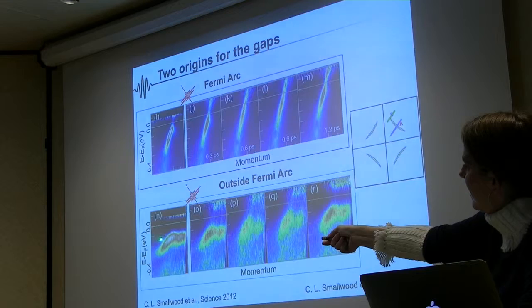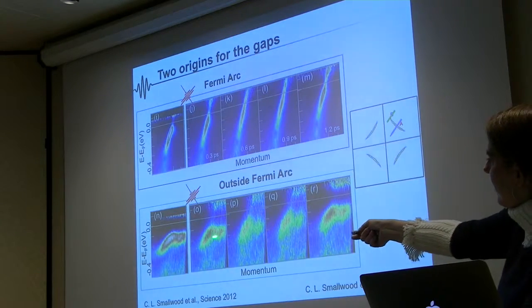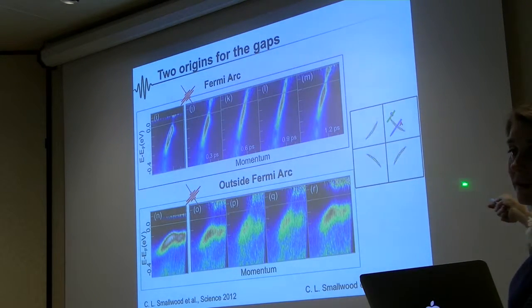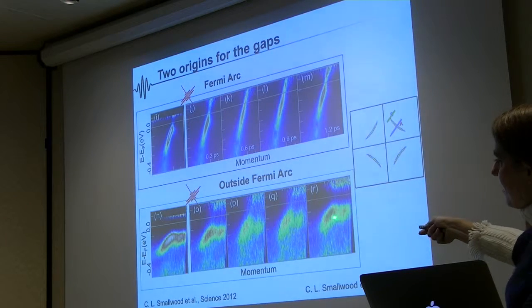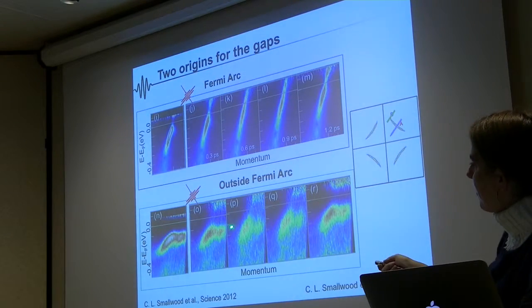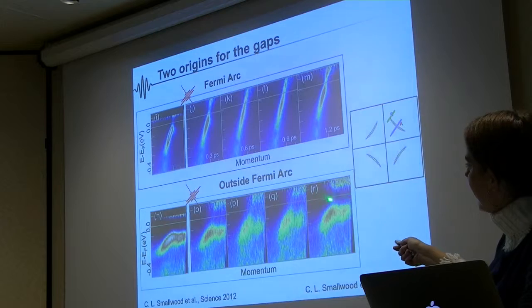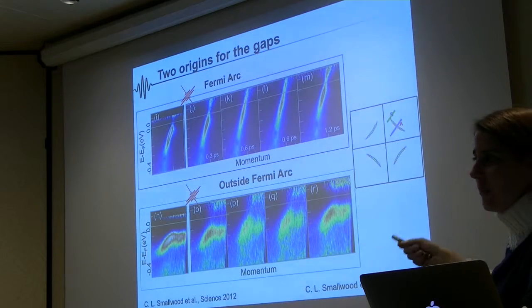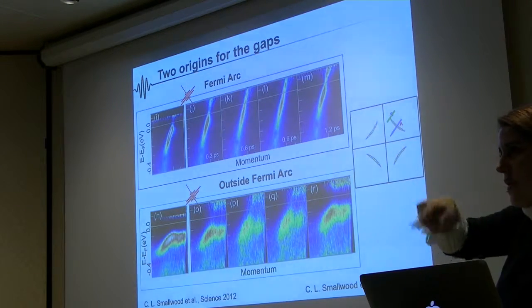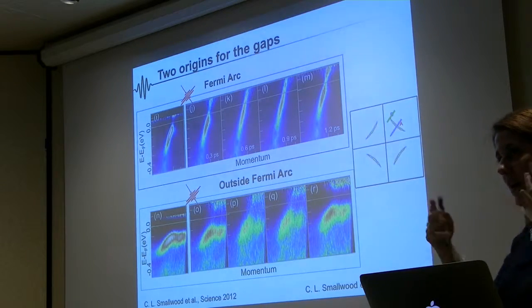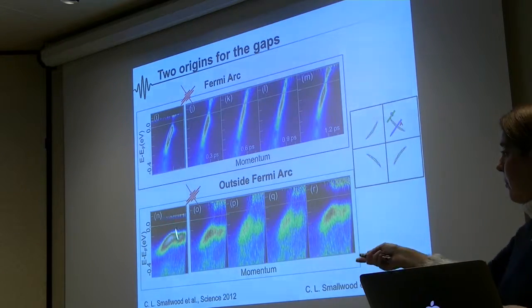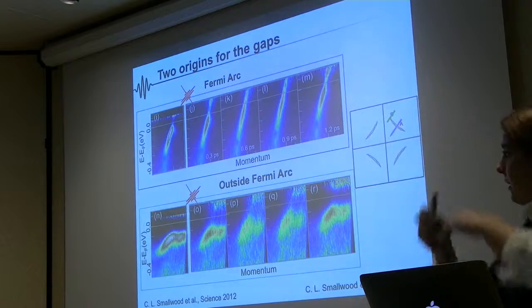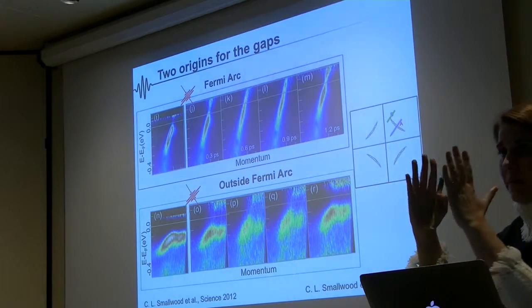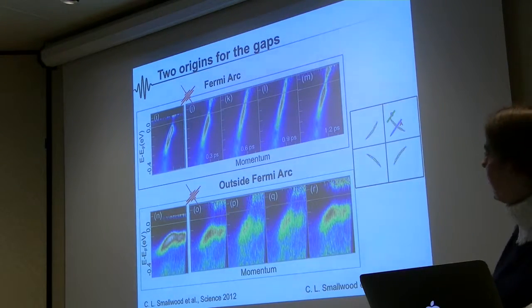What you see is that there is some suppression of spectral weight, then eventually it starts to go back to equilibrium. So you gain back the intensity, which is the spectral weight. But you see it's as if you are creating something inside the gap. If you think about the typical BCS model, you have a gap, with 2 peaks. What is happening as a function of time here is that you are filling in the gap. While here, the 2 peaks are coming close, you are closing the gap. So this is telling you that there are 2 different dynamics going on.